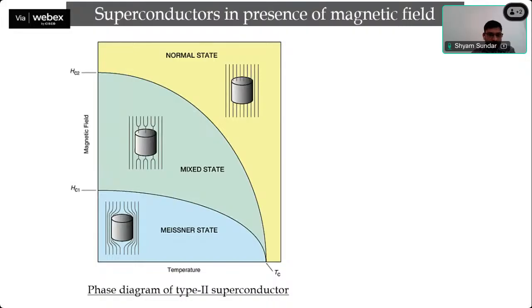Further, if you are in the superconducting state and you apply a small field and keep increasing the magnetic field, initially it is all shielded up to a field called HC1. But when you apply a magnetic field higher than HC1, the magnetic field starts penetrating into your sample in a very specific manner, which we call the mixed state.